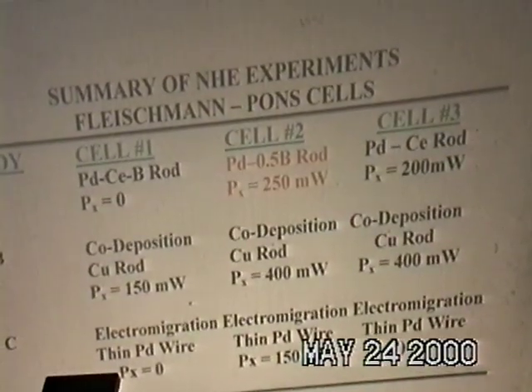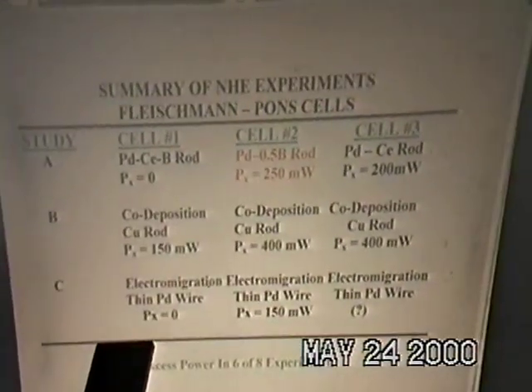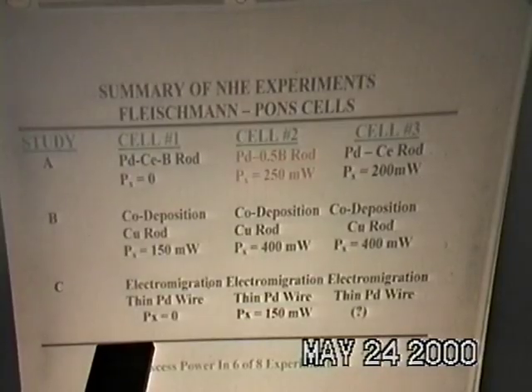The Fleischmann Pons calorimetry, I ran various experiments. Some rods I took with me, these 2 were made by NRL, palladium cerium boron. The second one is palladium boron. The third one is the palladium cerium given to me previously by Martin Fleischmann. And that will be what I'm talking about today, these top 3. I also ran co-deposition. That's the Szpak-Boss method, where you deposit palladium out of solution at the same time it's loaded with deuterium. All 3 of those produce excess heat.